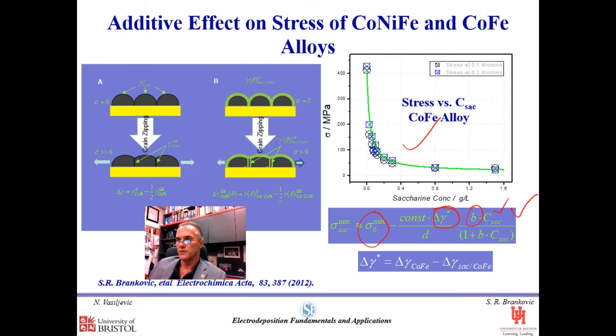But what I try to convey to you is that this is only true if you run your process in such a way that the saccharin or additive that you use adsorbs on the surface and mitigates the stress level. If you run your process in such a way that you have saccharin, for example, in the solution, but the potential on the surface is at some far away place where no saccharin is present, you will still have a high stress deposit. So it's essential that you understand where the additives that you use in your process adsorb, at what potentials, and that's how you actually end up being effective in terms of the design of additives for your electrodeposition process. So it's not just using the right additive, it's more than that. It's using your additive and running the process at the right potential with the right current density.